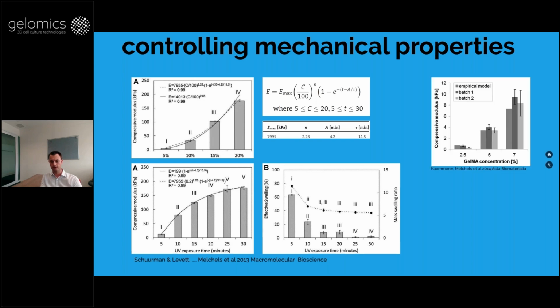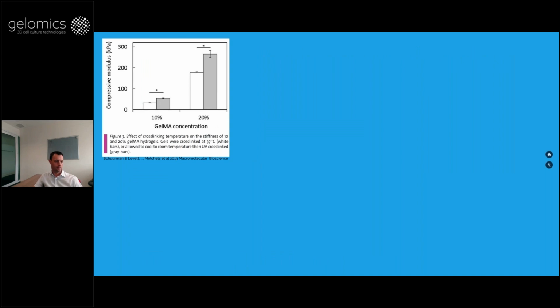Later, when we started using this for cancer models, we synthesized new batches and did the same characterization. You can see here that it's really quite reproducible, which is not that common for natural materials. We were quite happy that we could reproduce this. One other thing that we noticed at the time was that if the precursor solution was left to stand for a while before we turn on the light, that actually led to an increase in the modulus. And this is only a small increase here. We didn't give it too much time, but it was a single observation and we reported it, but didn't look into it much further at the time.